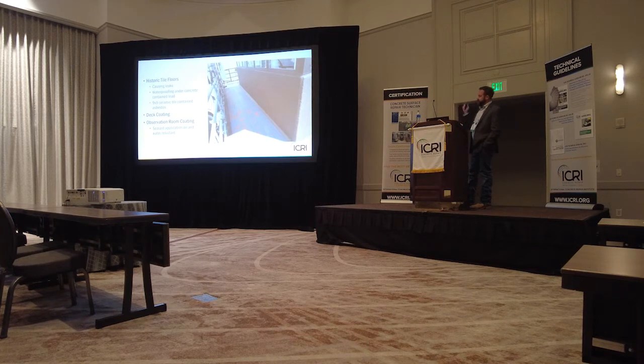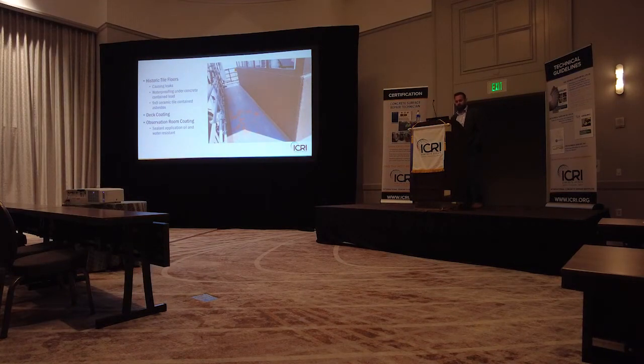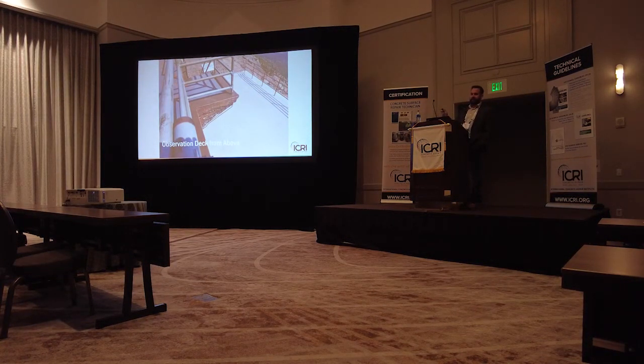This residence patio was actually the culprit of the leaking down into those walls. It actually exposed itself in some areas four to eight feet below, where it would cause efflorescence and escape out through the concrete down below. The new observation deck is a precast structure with a coating over the top of it — you can see some of the delamination in the coating. That damage had been there for a while, and somebody decided that paint may actually extend the life of that landing.